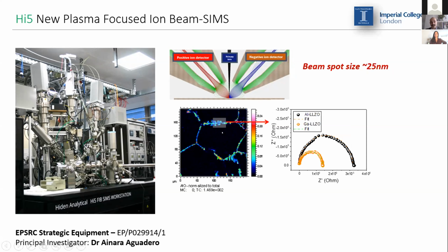Actually, we compared just the bulk by milling a micropillar of aluminum LLZO and gallium LLZO, and we confirmed that gallium LLZO has a higher lithium mobility when compared to aluminum. So please watch this space.